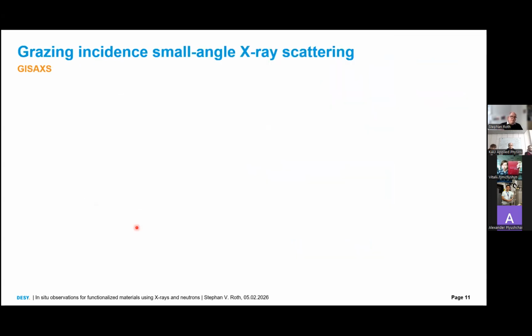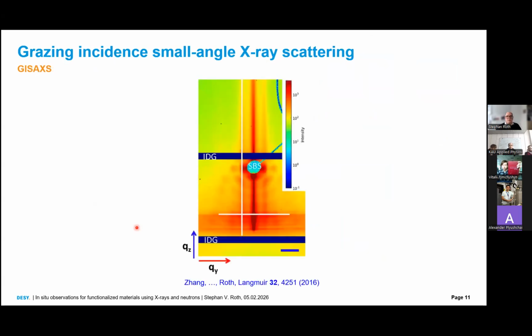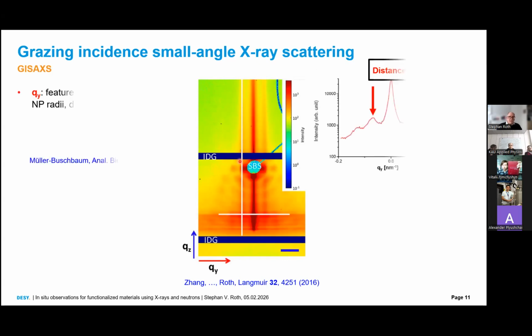When we now move our detector farther away, we are looking in the small angle regime, and this is a typical scattering pattern. These are just 100 nanometer polystyrene colloids sprayed on a silicon wafer, and you see a wealth of structures again. You see here the dots, which stem from the more or less regular arrangement of these spherical colloids. You see here the sample horizon. You see here resonant diffuse scattering. You see here strong Bragg rods, indicating that we really have a preferred nearest neighbor distance.